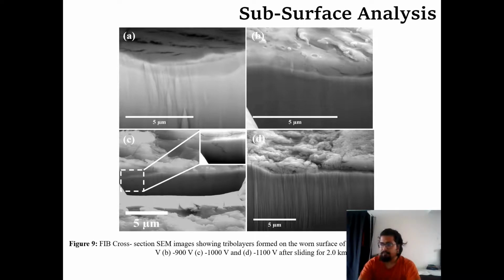Subsurface analysis confirms the idea of three-body wear, because we can see in C and D how they are damaging the layer as well as the substrate. The cracks within the layer are also defined: due to the high load as well as the long sliding distance, one possible crack formation can be shearing, shear stress based cracks, and in some cases it was fatigue as well.